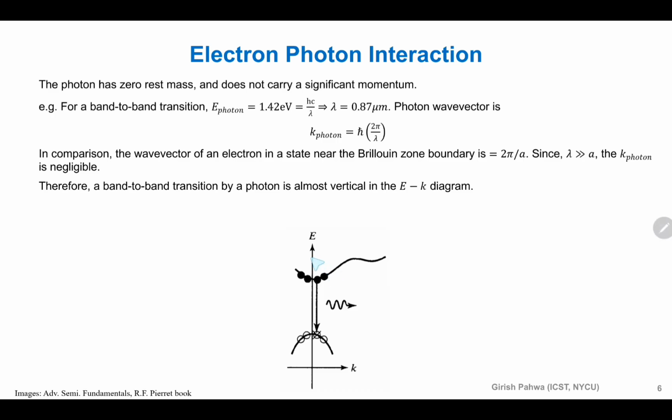Now assume that I don't have a semiconductor which is like this. So this is a direct band gap semiconductor, with k equal to 0 and k equal to 0, conduction band minimum and valence band maximum aligned in this case, right? So this vertical transition is possible. Assume I had this valley somewhere here, as in the case of silicon. Will a photon and electron transition be probable?